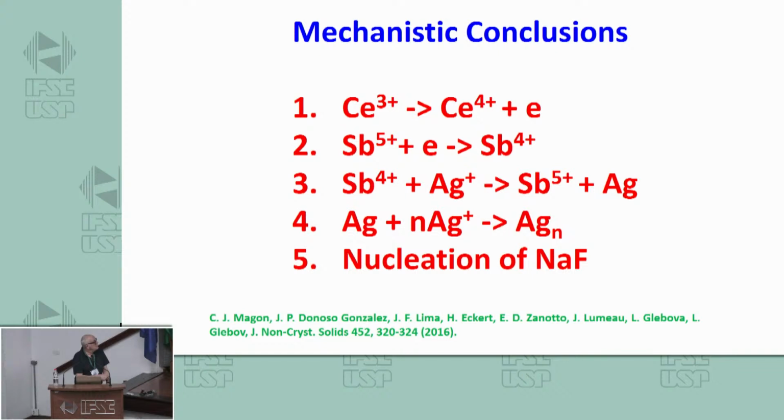But then also, in part, the antimony 4+ can react with silver plus that is also present in the glass to cause a reoxidation, and then we form silver nanoclusters. This happens upon thermal treatment, so when heating this material. And in fact, the silver nanoclusters can be detected by optical spectroscopy. So basically, this is something observable, but principally only by optics.